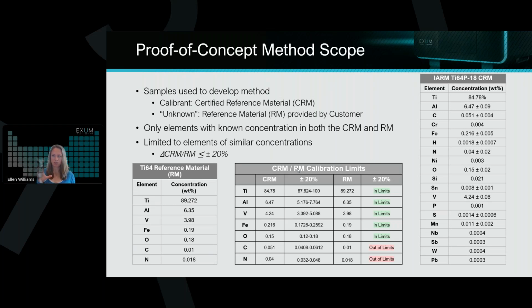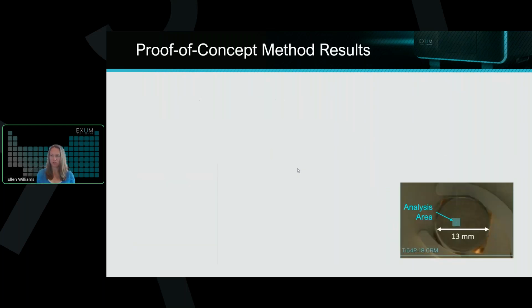But what we did was use these two samples, and we did an optimization process of sample prep. So how we pelletized the powders into these little pucks that you can see here. It's a pretty straightforward process. It's just a matter of applying a bit of hydraulic pressure so that we aren't putting a chamber full of powder into our instrument with the lasers. We essentially just have to adhere them to something.